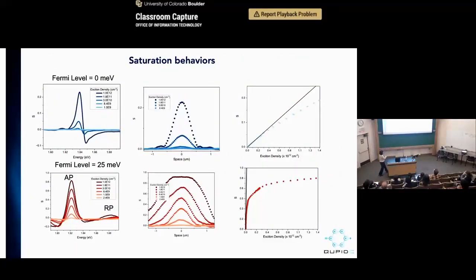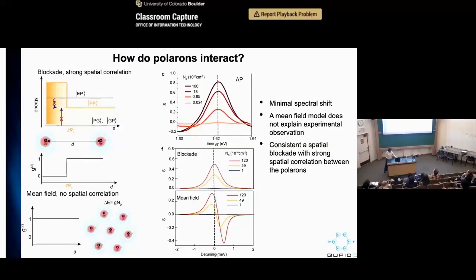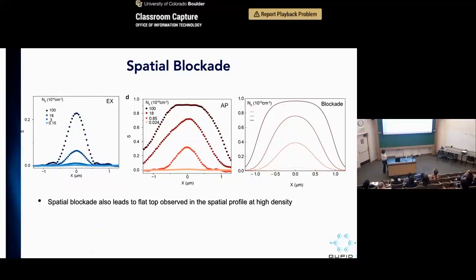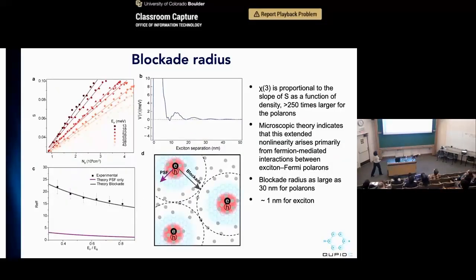I'm just going to say then we can extrapolate optical nonlinearity by looking at how this transition saturates, and the polaron saturates at a density that is 2 orders of magnitude lower than the excitons. From that, what you can extract from this nonlinearity curve as a function of density is the blockade radius in this case, and it turns out to be about 30 nanometers for the polarons, in comparison to about 1 nanometer for excitons. And this, again, is coming from these Fermi seas mediating this long-range interaction between the excitons.